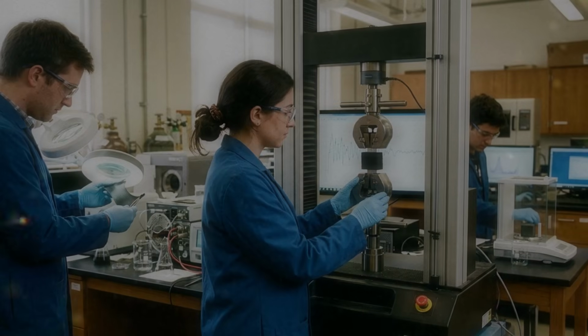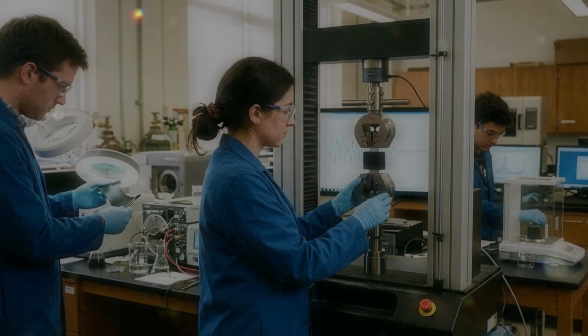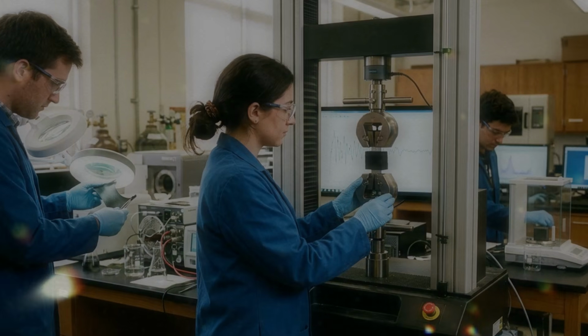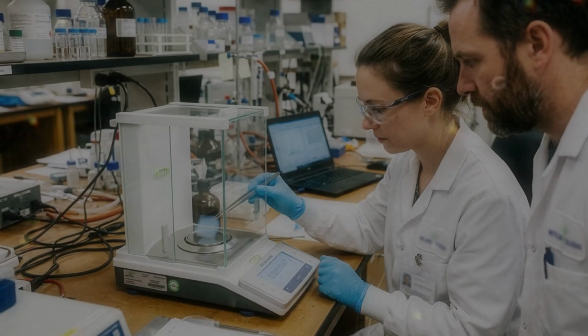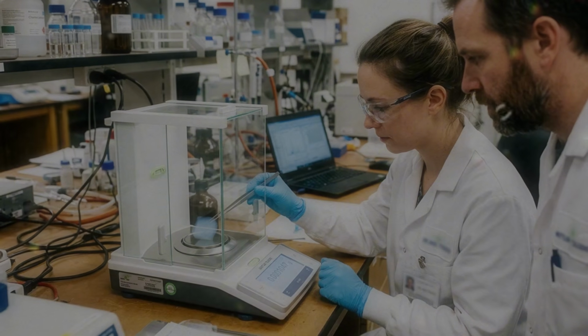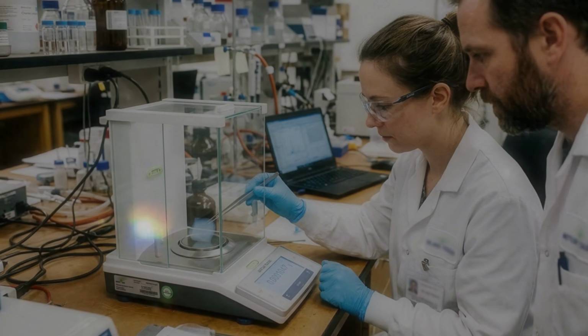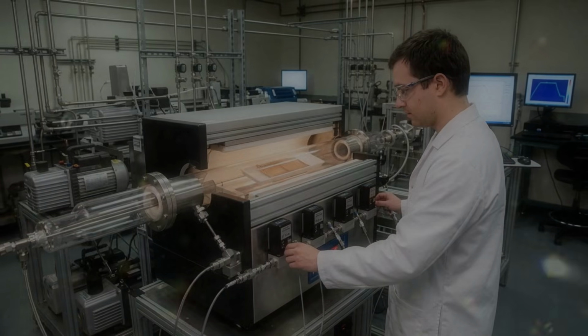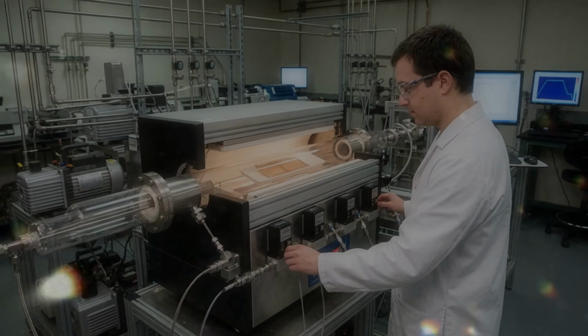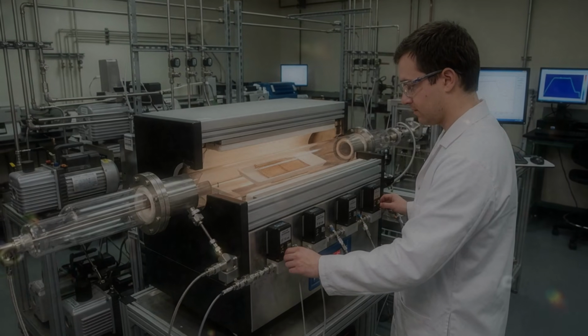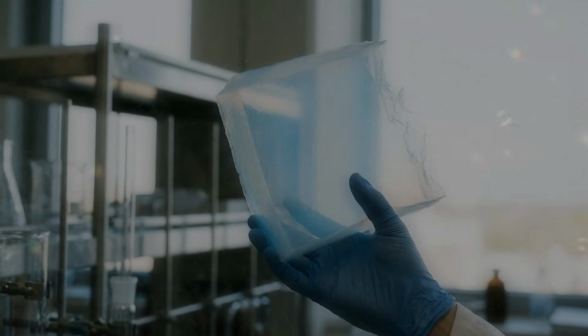The graphene sheets are connected enough to span the sample. Their wrinkles create spring-like behaviour. Nanotubes can cross open gaps. The walls meet at angles that help the cells resist collapse. During compression, the largest and weakest pores often begin closing first. As the sample becomes denser, more walls touch, and further compression becomes harder.